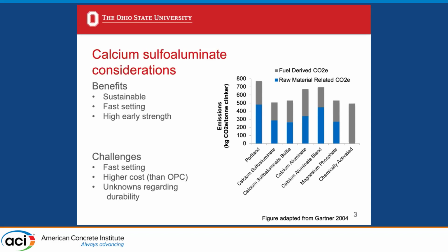As Cameron mentioned earlier, you can obtain set in as early as 5 to 10 minutes without retarder. And along with that fast setting time comes also high early strength gain rates. So we can use these materials to accelerate construction schedules and perform rapid repairs.